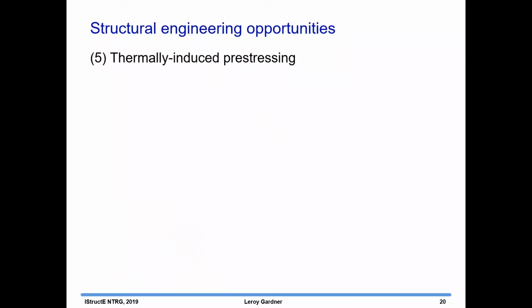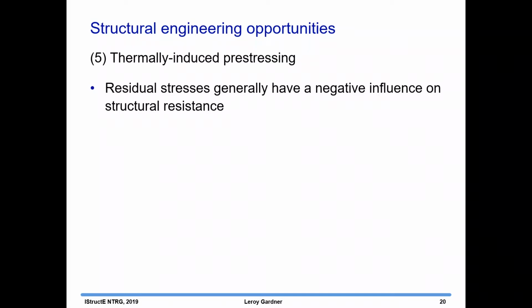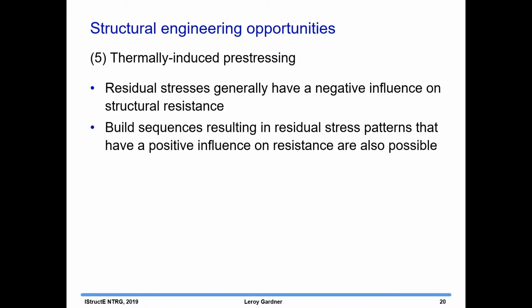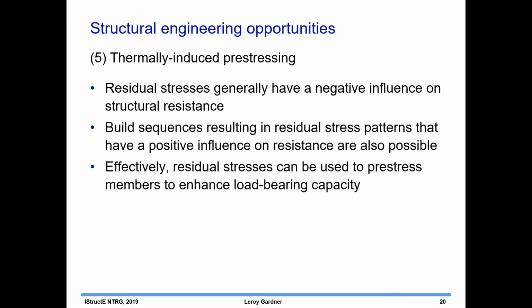Residual stresses are often part of the metal 3D printing process. And residual stresses generally have a negative influence on the structural resistance. But with 3D printing, the sequence in which you build up the structure is such that you do have some control over the thermal stresses that get locked into your structure. And so potentially you can think of, instead of residual stresses being negative, think of pre-stressing your members against any subsequent applied loading.